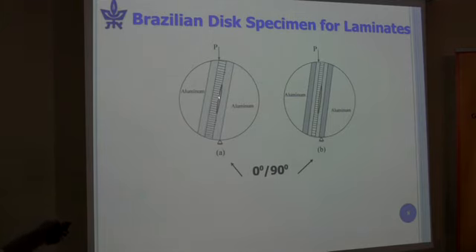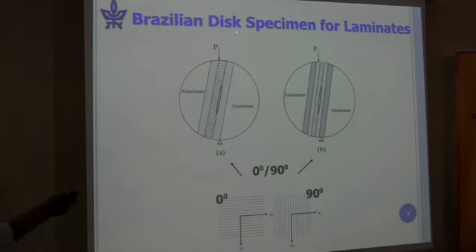Okay, the load is going through the center of the delamination. Here is the delamination. And by rotating the specimen, we get a full host of mixed modes. So again, to explain the 0 and 90, the x1 direction is along this layer, as I'm showing you. And so here in the 0 degree, the fiber's along x1, x3 is coming out at you, and x2 is perpendicular to the delamination. And in this layer, we have fibers in the 90 degree direction, so they're coming out at us in the x3 direction.